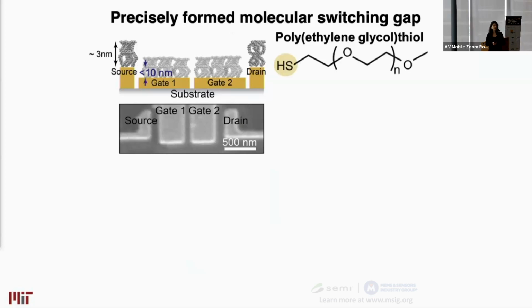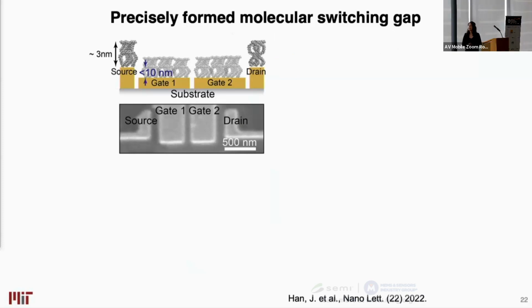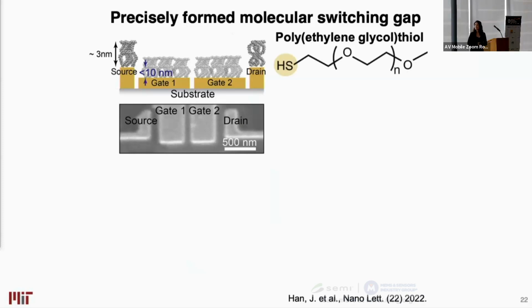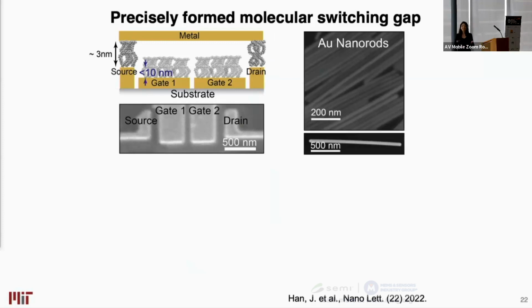The molecules are assembled through a self-assembly process. And the next step would be to introduce the top contact without inducing any damage to the molecular layer. Various different techniques can be used, and throughout the years, we've developed a variety of techniques. One that I'm showing you here is using colloidally synthesized gold nanoparticles as actual building blocks for the top contact of these devices. So the SEM image shows these nanorods that are formed in solution. When you take a droplet of them, put them on a surface, and image them, they're disordered.